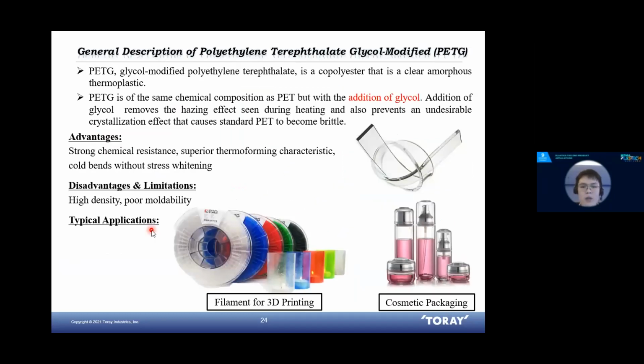So PETG is commonly known as polyethylene terephthalate, PET plus glycol. Mainly, this glycol is added to remove the hazing effect seen during the heating of the plastic. The PET with glycol is able to stop the crystallization of PET at high temperature, which makes PET opaque and brittle. One of the advantages of this PETG is very good chemical resistance to common materials such as soap or other cosmetic material. The disadvantages of this PETG are the high density and the difficulty of the molding process.